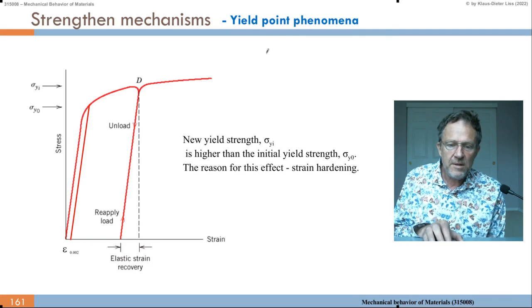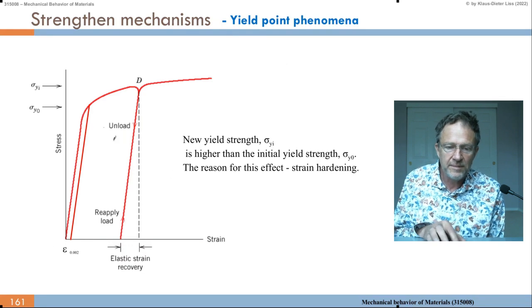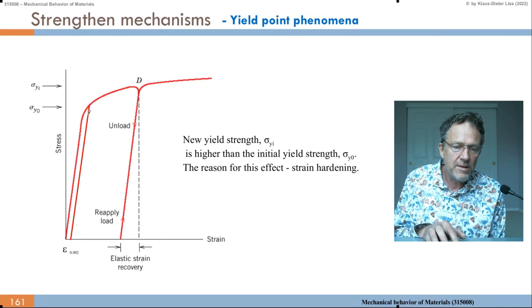We have the yield point phenomena. So if we have an annealed material, say annealed copper, then we get a sigma yield 0 for the first stress-strain testing. So we go up here, this is elastic behavior, then we go plastic, and then we unload and end up here. So this is our plastic strain as we know, and we count that from 0.002. So if we don't unload and we continue further from the 0.002, this is just a convenient number so that we can estimate when it starts to yield. So we call that point sigma yield 0.